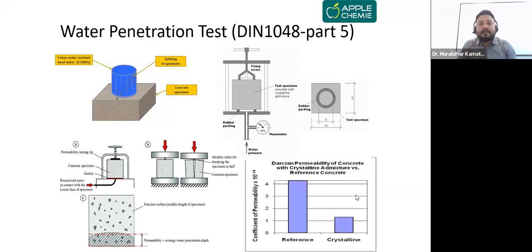But what is the coefficient of permeability? You are going to cast two cubes, one with crystalline mix design and another without crystalline mix. Okay, and you will cast three cubes at a time. You will keep them for cycles. There will be 4 cycles: 72 hours of water pressure, then 48 hours of drying cycle. This is one cycle. Then again you will repeat 72 hours of water pressure and 48 hours of drying period. Similarly, the third cycle and fourth cycle.